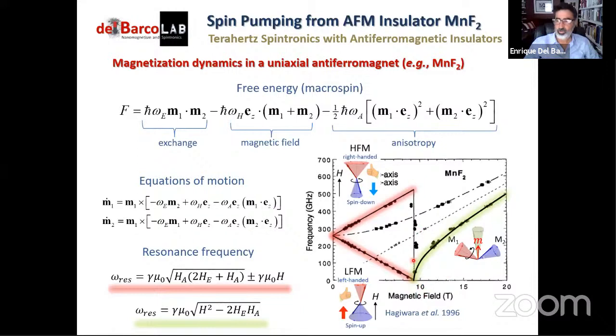So this transition between these two regimes can be solved analytically. And in this case, as you can tell, the system actually develops an equilibrium magnetic moment. This is because once you are perpendicular, you have the sublattice magnetizations perpendicular to the applied magnetic field, and they will cant slightly towards its direction, and an equilibrium magnetization will develop. So this is intrinsically different behavior from here, where the net moment is only dynamical. If the system is not undergoing antiferromagnetic resonance, there is no net magnetization below the spin flop